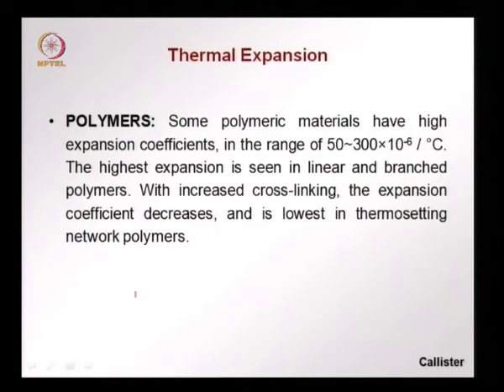So, we have a low coefficient of expansion. On the other hand, in polymers we generally have high expansion coefficients in the range of 50 to 300 times 10 to the power minus 6, sometimes one order higher than what we saw in ceramics and metals, and the highest expansion is seen in linear and branched polymers. If you remember, these are the polymers which have van der Waals bonds between the chains, these are weak bonds, and we do not have covalent bonds between the chains. There we have higher expansion, whereas in cross linked polymers with increasing cross linking, the expansion coefficient decreases, that is, there is less thermal expansion when the cross linking is stronger. And in thermoset network polymers we have the least thermal expansion, where you have strong covalent bonds between the different molecules and you have a stiff network structure.